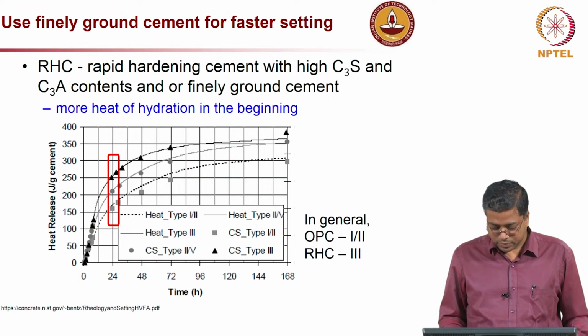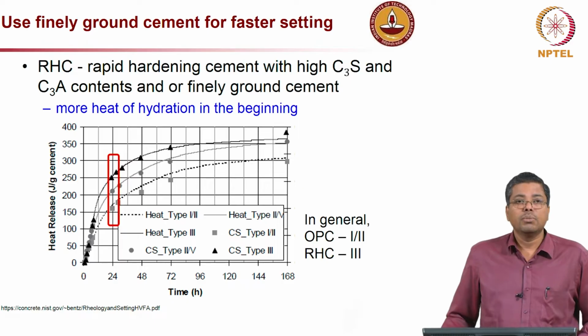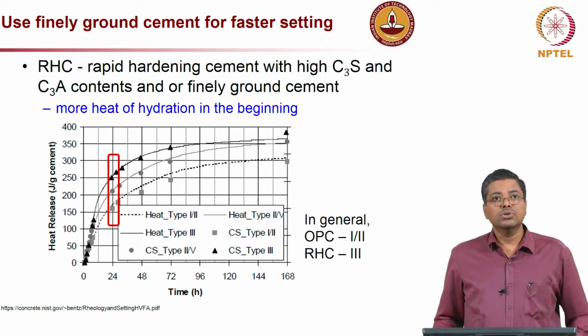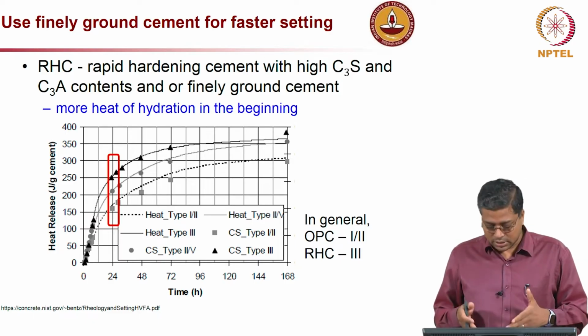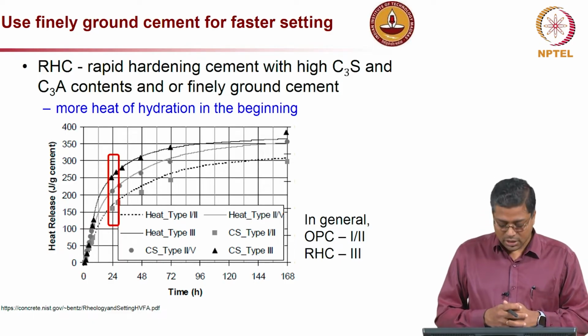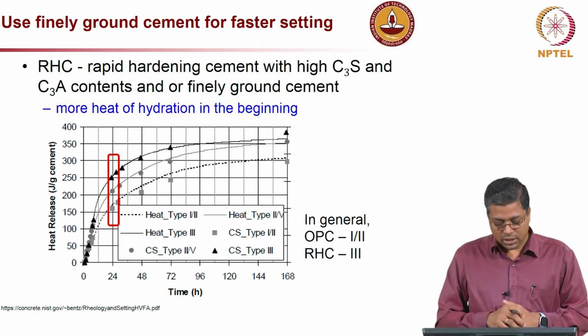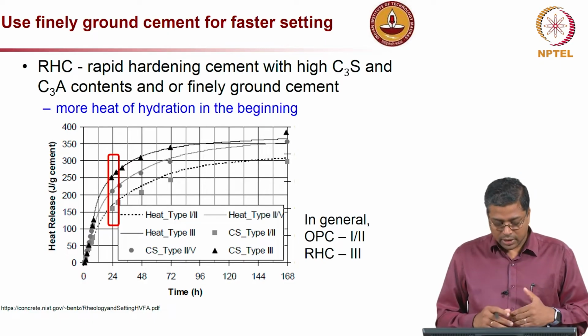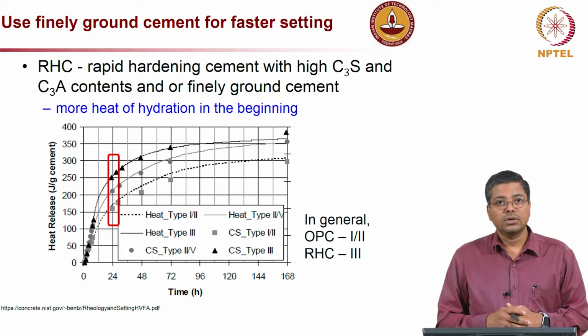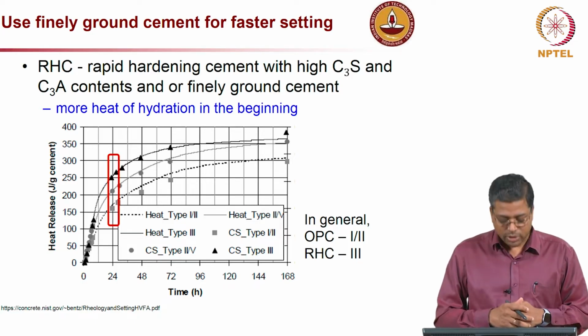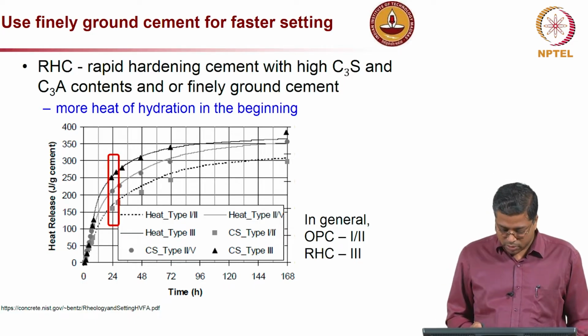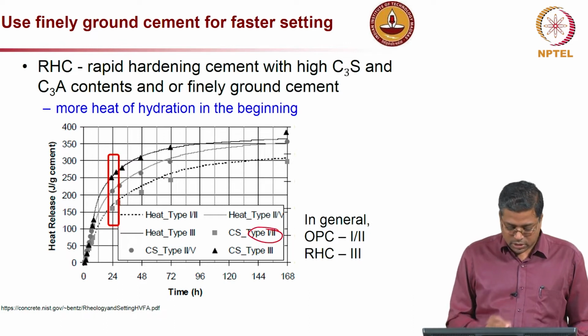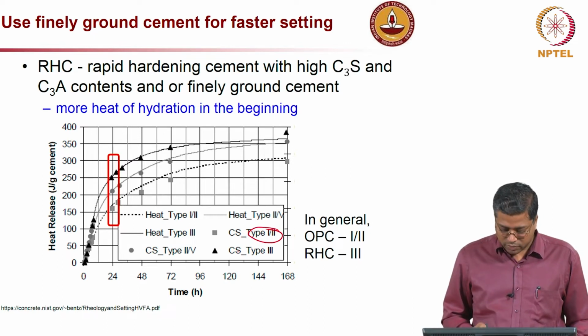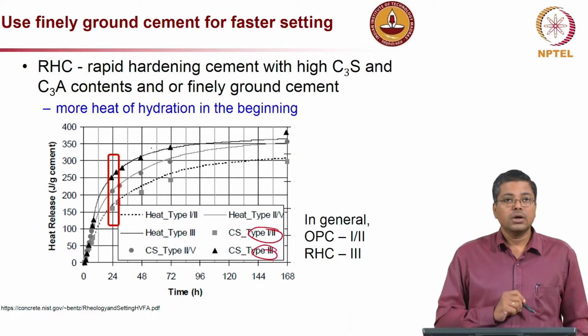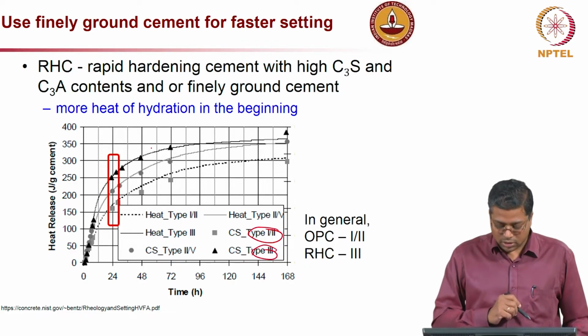So, you have to really consider various measures on how to ensure that the concrete is actually setting fast enough. One way to achieve that is by using finely ground cement. Basically, the idea here in the graph, you will see type 3 cement, which is the designation used in the US, and you have type 1 or 2 cement, which is the usual normal cement. You can see here the normal cement type 1 or 2, which is the square markers, and the triangular one, which is type 3, is the finely ground cement.